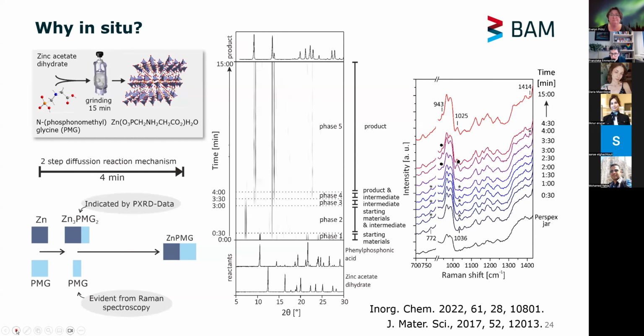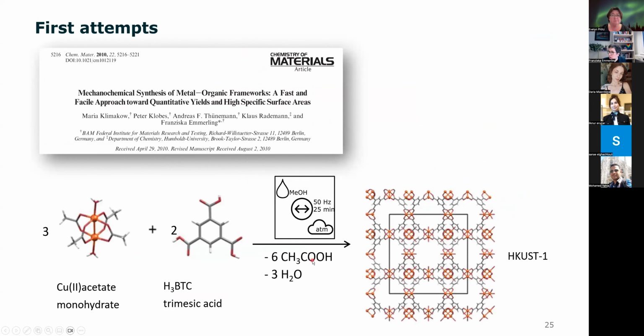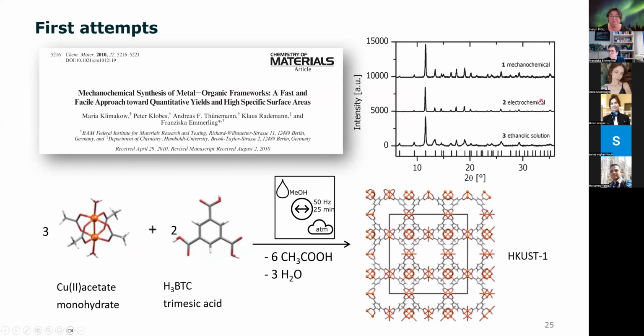And this is also something that we tested with the first reaction we did, or the first publication we have with MOFs and mechanochemistry. You can see that's 15 years old. And there the focus was, can we really make MOFs using mechanochemistry? And then we compared to other synthesis routes. And as you can see here, we milled about 25 minutes. Back then, my PhD student was more or less kicked out of the labs because it's also rather noisy if you perform mechanochemical reactions. So it was not optimal, to say the least. But it worked nicely.